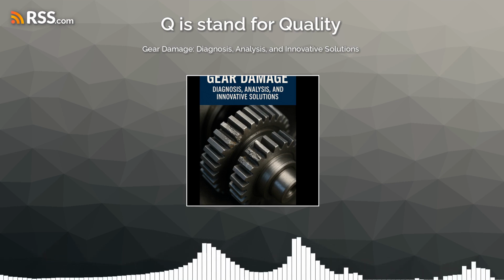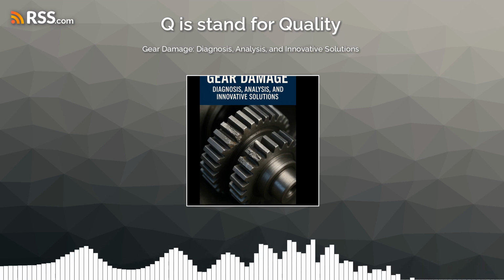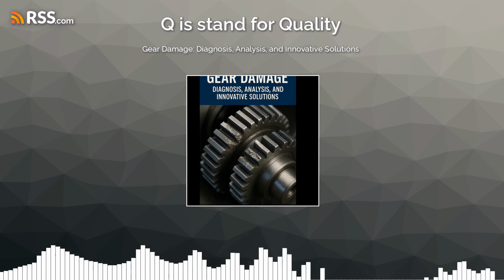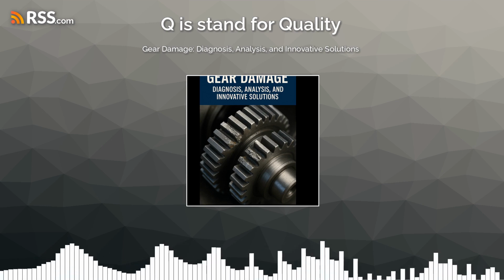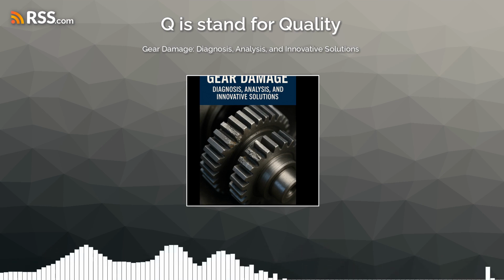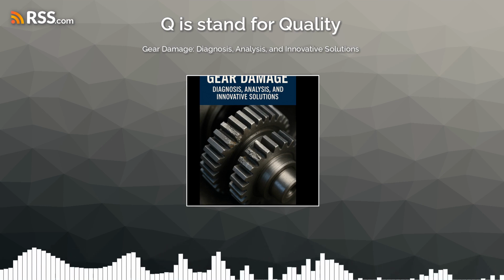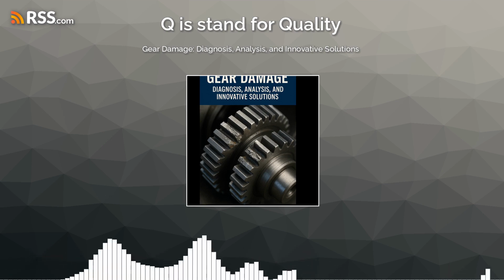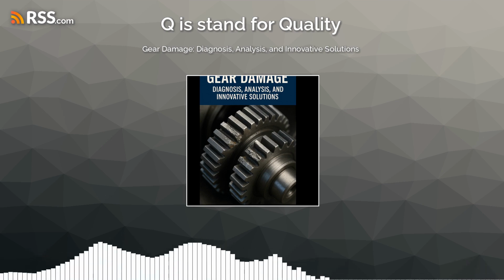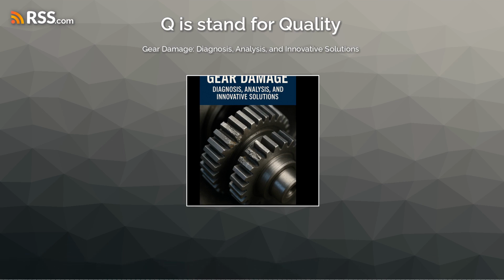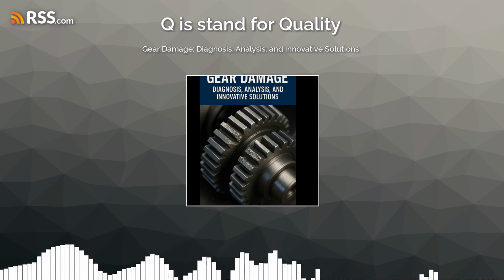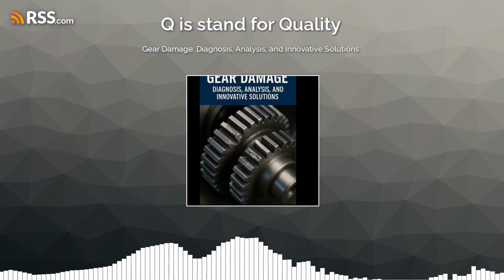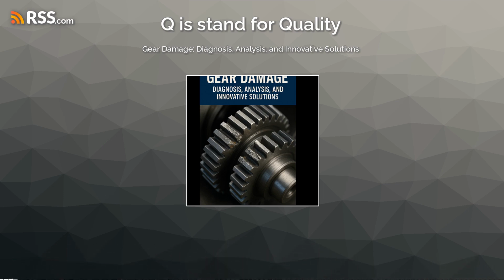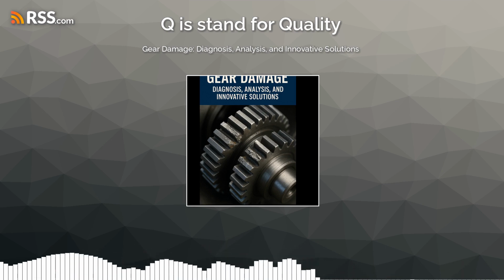Can they work with metal gears? Yeah, the good mechanical and tribological friction and wear properties of engineering polymers like POM, polyoxymethylene, PA, polyamide like nylon, or PEEK, polyether ether ketone, mean they can actually mesh effectively with metal gears. Creates hybrid possibilities. Though, interestingly, the surface quality of the metal gear really affects how the polymer gear wears. A rough mating surface will chew up the polymer faster.